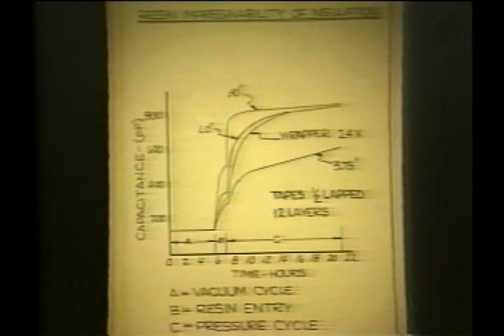What they did was to make up several samples and tape them up with the same type of material, the same number of layers or half-lap layers of tape, and the equivalent number of wrappers. And they measured the capacitance of the winding during the vacuum pressure impregnation process. The idea here was, as the resin displaced the air in the winding, the capacitance would change, and when you get to the point where the capacitance doesn't change anymore, that would indicate that full impregnation has been reached. Now, we didn't show all of the data that's available in this report, but we're looking selectively at tapes varying in width from 0.4 of an inch to 3 3/4 inches, and comparing that to a wrapper.